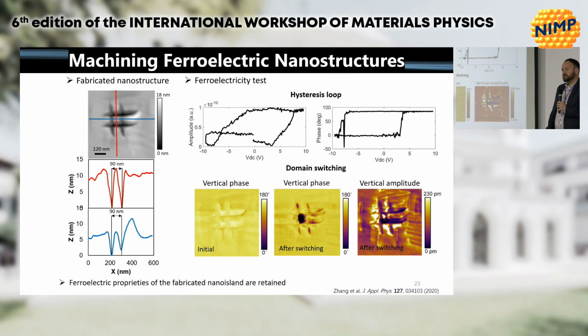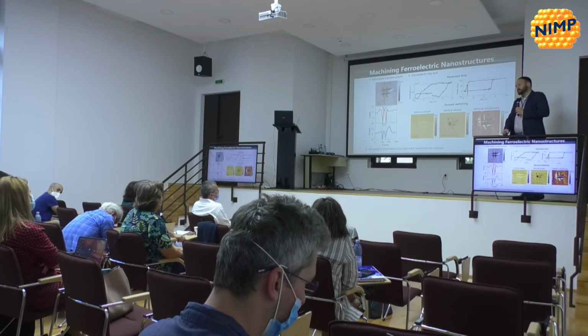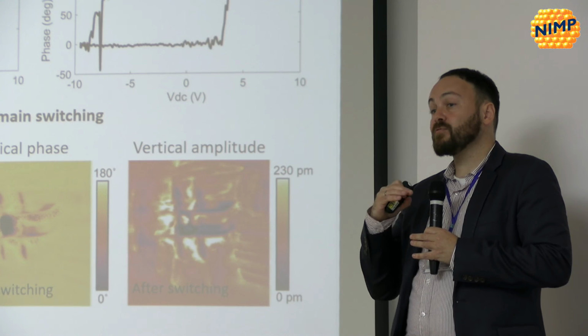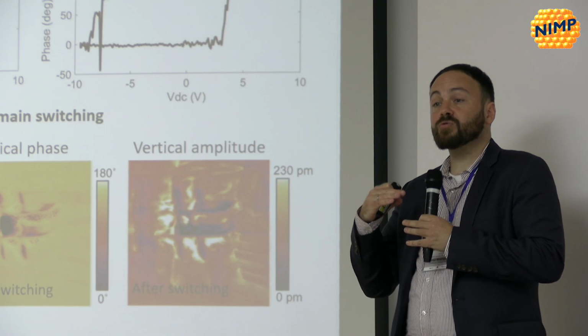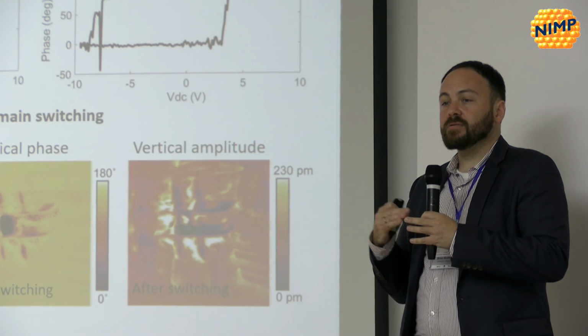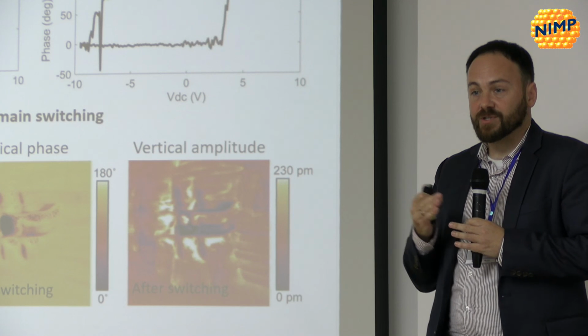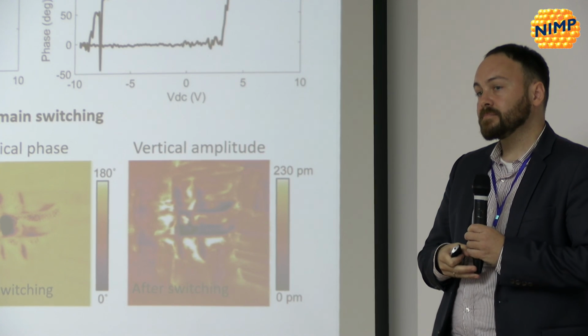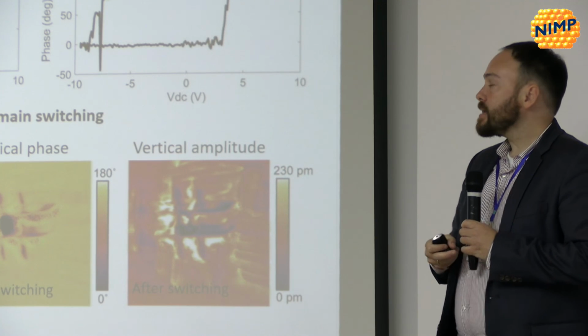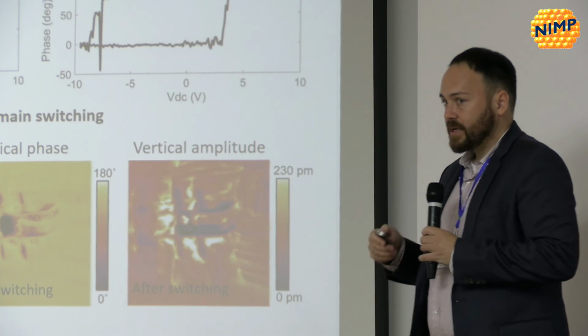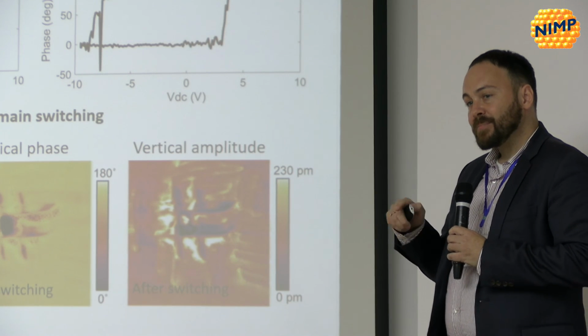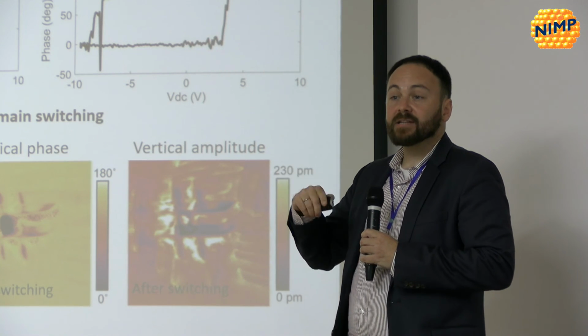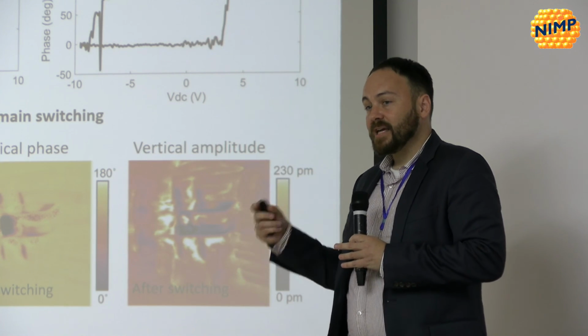And the second question, if I understood correctly, your interpretation suggests that you heavily squeeze your dead layer, and consequently you have high tunneling current. It's like this? Yeah, I probably missed a step in the explanation. I think we're squeezing the dead layer, which allows for injection of charge, and at the point where you're switching, that charge can be transferred across, because of the need for screening at the time you're switching. And I think that's what's resulting in that enhanced current. And looking at the difference in the amplitude, you have to squeeze it quite a bit. Yeah, we had to squeeze it quite a bit. The forces were relatively high. But if we look at the amplitude of the loops, the amplitude is increasing with force. So the response is getting higher, even though we're pushing harder.